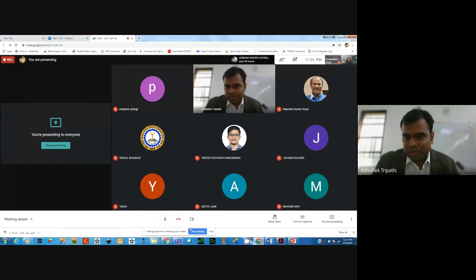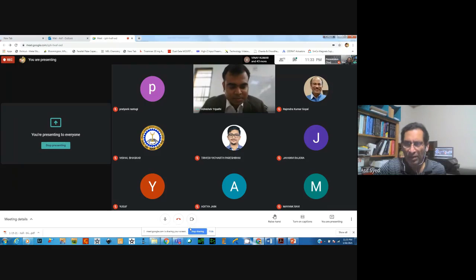So we have another question from Mr. Naveen. He's asking, can silicon carbide be used instead of diamond as an indenter? Yeah, you can use silicon carbide, maybe even on soft metals, but I won't recommend it for other materials, because as you indent, if the indent tip is deforming, you don't know the shape of the indent. So if you use metals and hard materials and ceramics, I recommend diamond. But if you use soft materials, soft metals, it's okay to use silicon carbide.